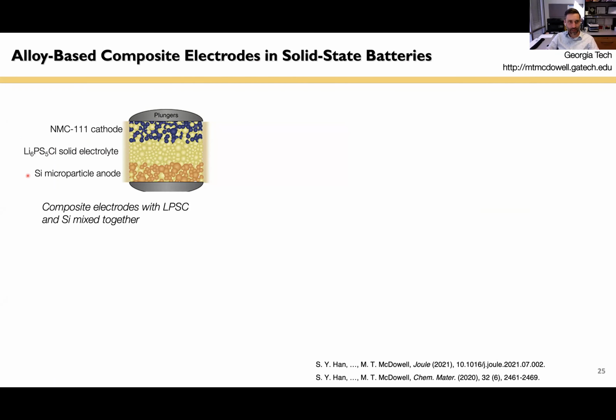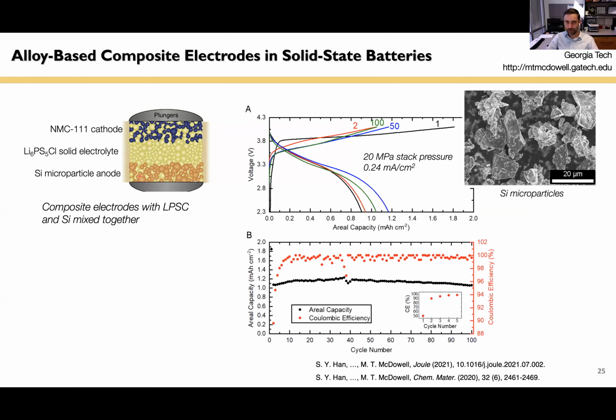But in these cells, we have an alloy-based anode. It's a composite where we mix, in this case, silicon particles with the solid electrolyte material, and we compress it to form kind of a pellet structure. And then on the other side of the battery, we have an NMC 111 cathode. And it's the same situation where we're mixing the active NMC material with the solid electrolyte. And so what I want to show you is first the performance of these types of batteries. So we use these silicon microparticles. These are just commercial Sigma Aldrich silicon microparticles, 5 to 10 microns in size.